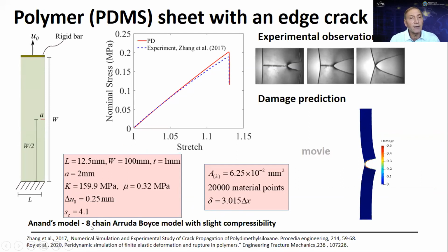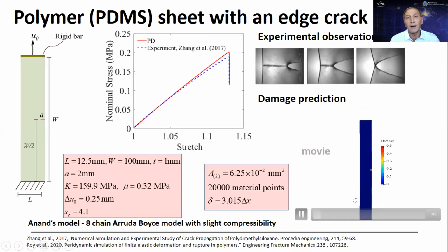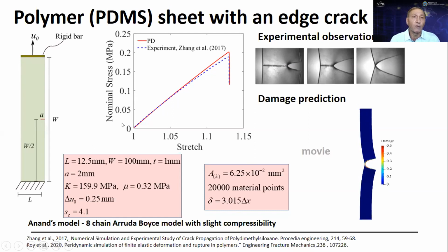We use Anand's model. That's basically the eight-chain Arruda-Boyce model with slight compressibility. And this is their experimental observation. And this is what we simulate as we are applying this stretch, and the crack starts opening up, and then it starts growing, very similar to what they observed experimentally. And also the nominal stress versus the stretch very nicely captures when the failure occurs.